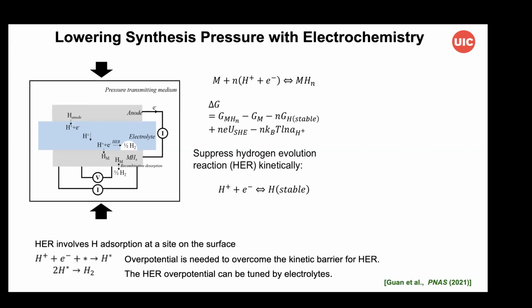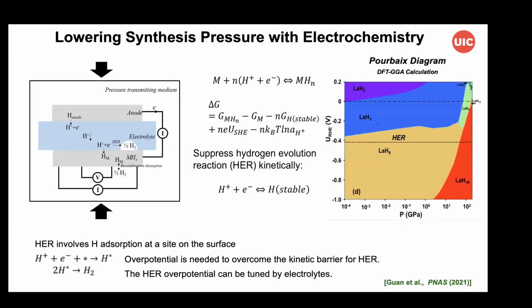And so to do this, one would put basically an electrochemical cell inside a diamond anvil cell and use an overpotential to overcome the kinetic barrier for this hydrogen evolution reaction, and then tune this with different types of electrolytes. This is all theoretical work right now, but it's very intriguing. And if you apply this to the lanthanum hydrogen system, you produce a phase diagram like this, which is known as a Pourbaix diagram, where we have this potential as a function of pressure. It's a log scale, but it shows that the lanthanum hydride is stabilized by this increasingly negative potential at quite low pressures. So quite intriguing.